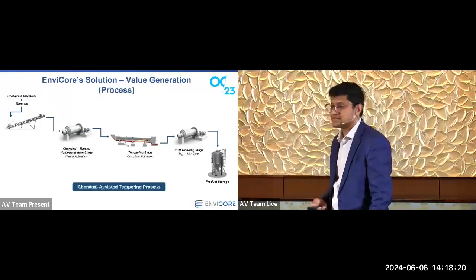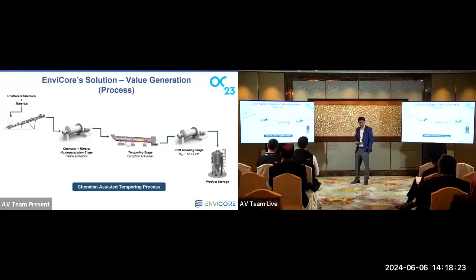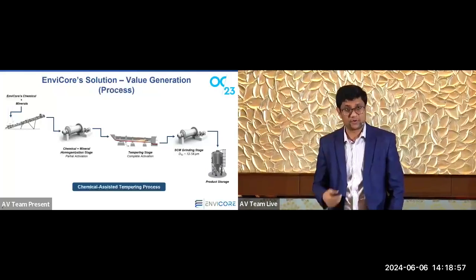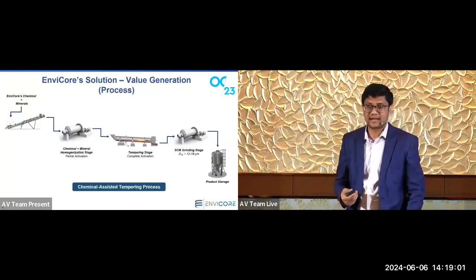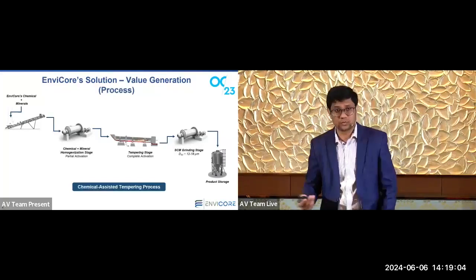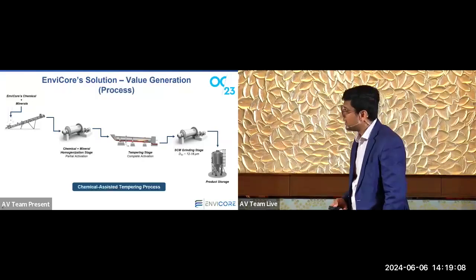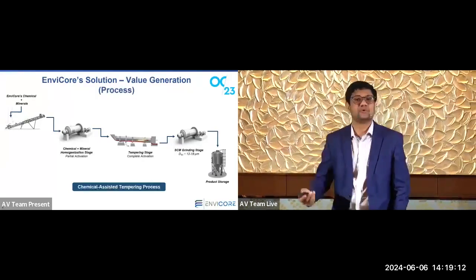And our process is divided into 3 interesting steps. Our first step is mixing or homogenizing our proprietary chemicals with the mineral stream in the desired ratios. We mix it in a ball mill or another type of homogenization process to achieve a partial activation of these minerals with the chemicals that we add. That material is then transported to another step, the tempering stage, where we get the complete activation of the material, going from inert or low reactive material to a highly reactive material. And finally, to comply with ASTM, CSA, and other standards from a fineness perspective, we go with the final SCM grinding, which can easily be combined with the clinker grinding as a co-grinding process. The overall process is called Chemical Assisted Tempering Process, or in short form, CAT.